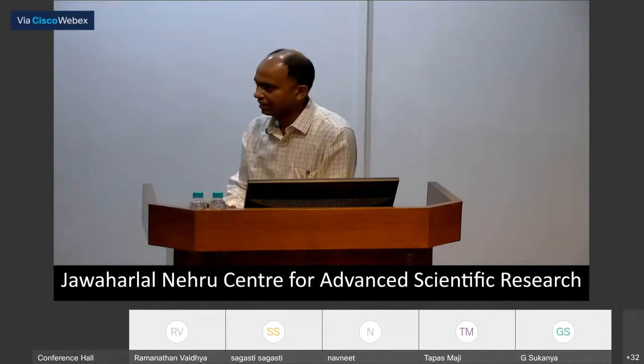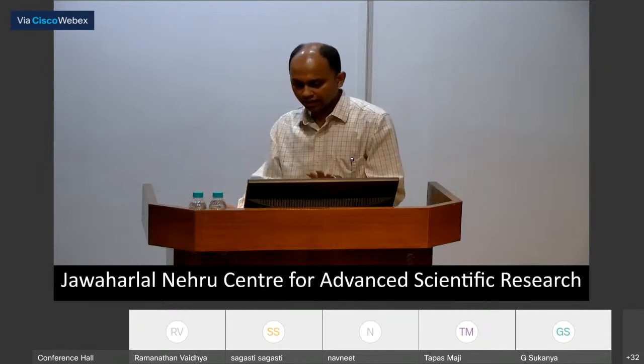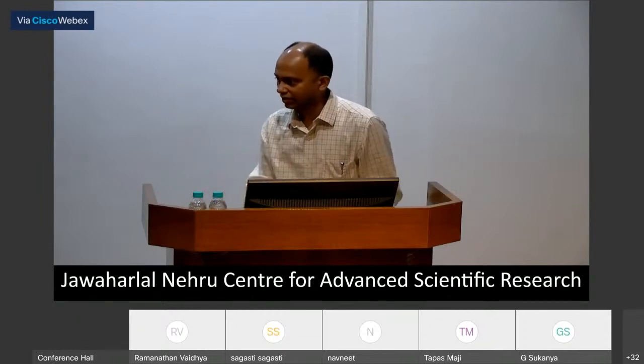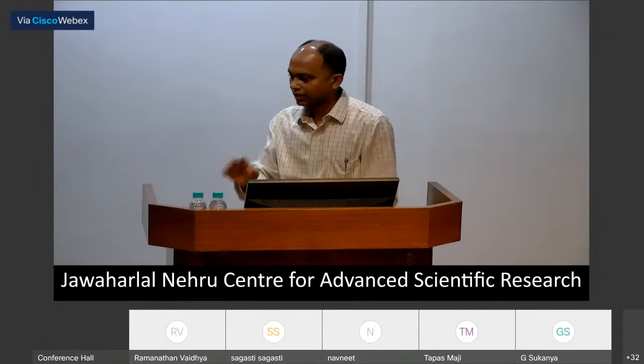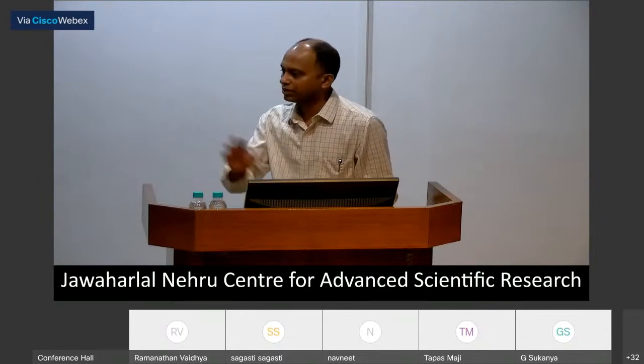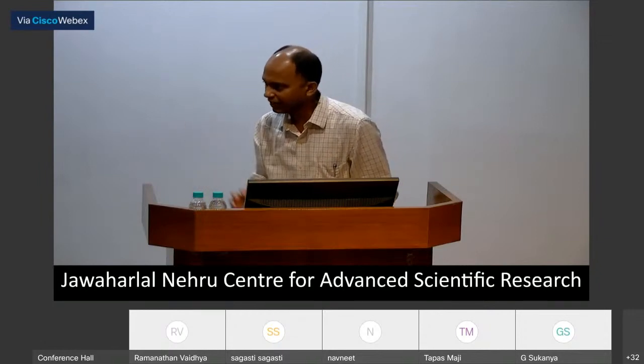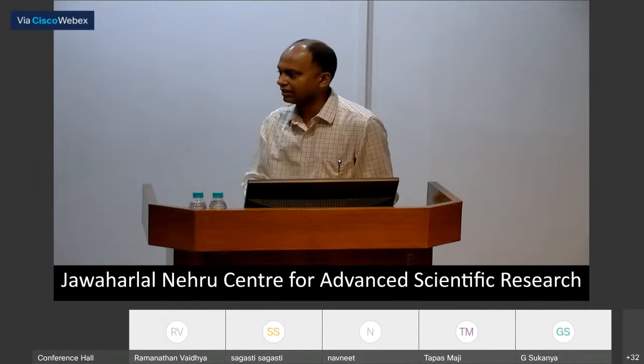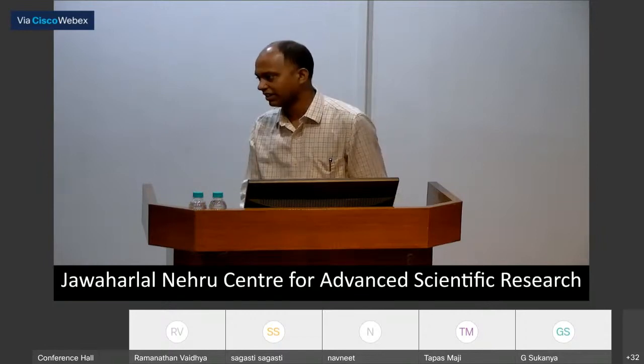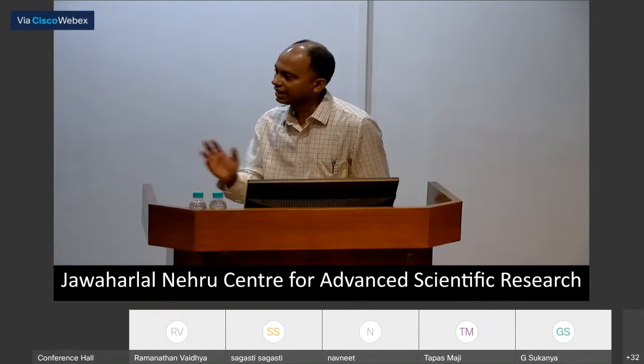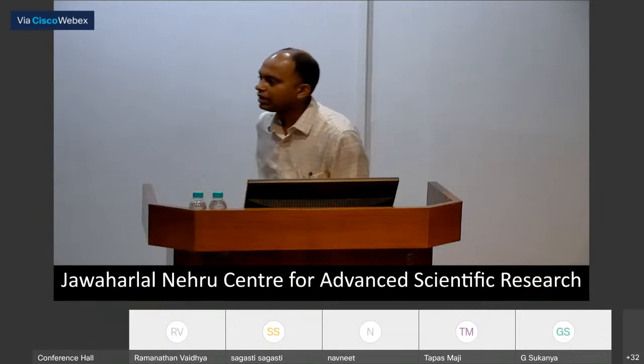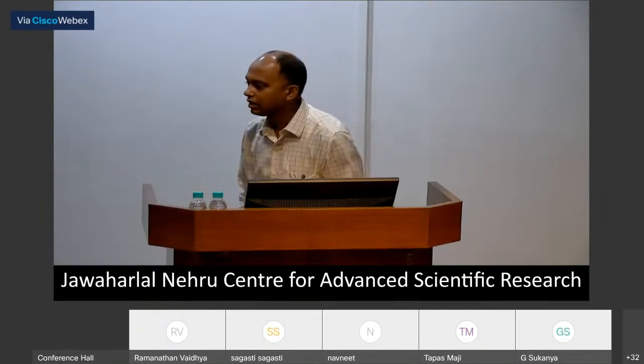If you see a particular TEM image, it's everywhere actually. In a particular TEM image, you will see 4 or 5 places. So it is everywhere in the sample, but the size is very small. The distribution is high throughout the material. So this happens in nanostructured thermoelectrics. Actually, the point is, how do you connect the observed efficiency to superstructures? Because I think their fraction is very small.